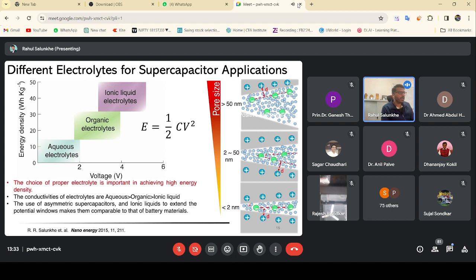Now on the other side, there are various types of electrolytes. We know that energy density is equal to 1/2 CV squared, and it is proportional to the voltage window. So what kind of voltage window? It is 1 volt, 2 volt, 3 volt. Depending upon the voltage window, our energy density will go on increasing. But the problem is that in the case of an aqueous electrolyte, we cannot go beyond 2 volt, because of the potential of the 2 electrodes. That's why with aqueous electrolytes we can go up to a maximum of 2 volt.